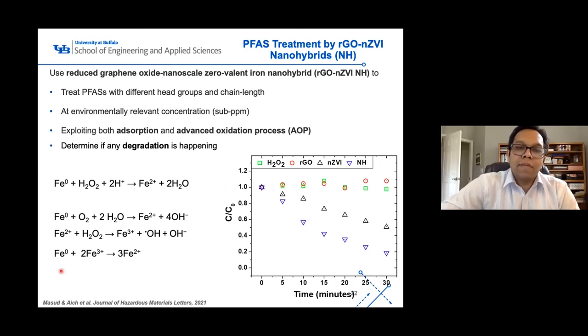So this is kind of the reaction mechanism that goes on the catalyzed surface. Iron zero reacts with the hydrogen peroxide and creates iron two plus. And then iron two plus eventually reacts with hydrogen peroxide to go to iron three plus and then create hydroxyl radicals or hydroxyl ions. Similarly, iron zero will also react with oxygen and water to give hydroxyl ions.